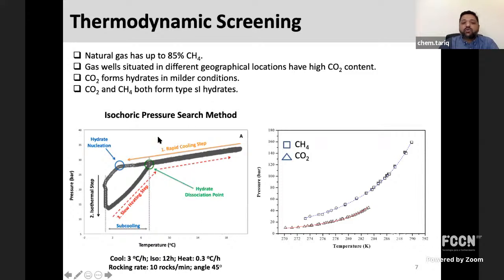And we have used this isochoric pressure search method. So in this method, what we do, we rapidly cool down the system, mix the gas and liquid, and then afterwards we leave it isothermal for a longer time, around 12 hours in this case, and then very slowly we heat it. So wherever these cooling and heating curves meet and intersect, this point is called the hydrate equilibrium point or hydrate dissociation point. And here you can see that methane is forming hydrates at a higher pressure compared to CO2.